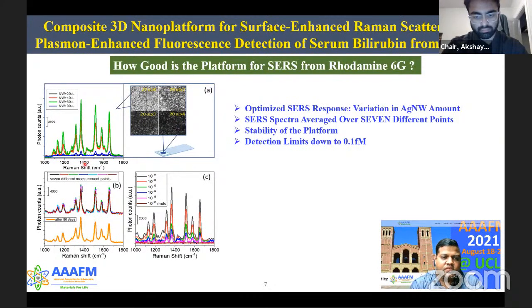And to acquire SERS spectra, we normally took 7 different measurements and then averaged. To test its stability, we also tested the stability of the platform after 80 days. And to know its limit of detection, we varied the rhodamine 6G molar concentrations. And as you can see, it can detect rhodamine 6G even up to the femtomolar level.